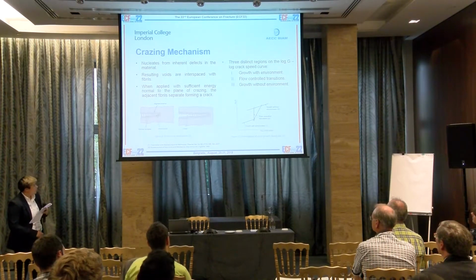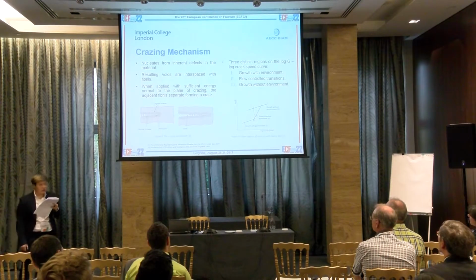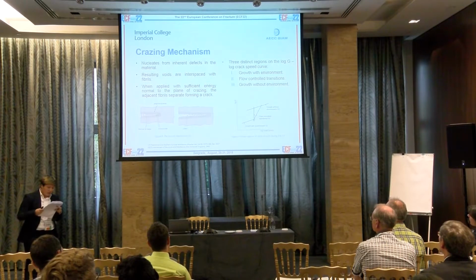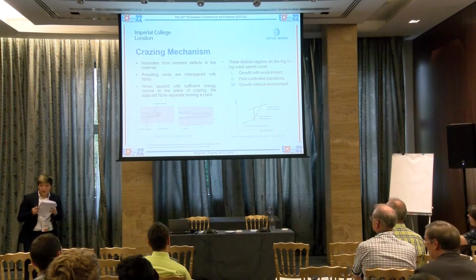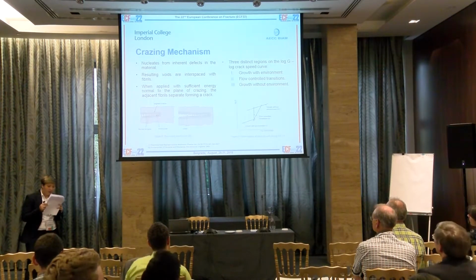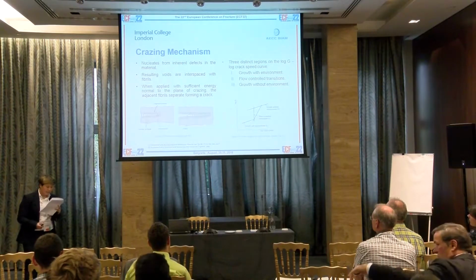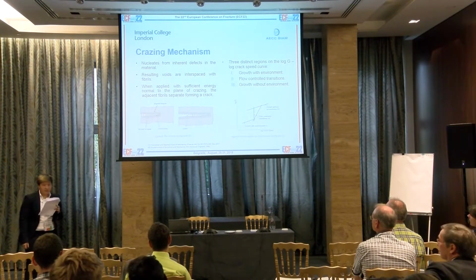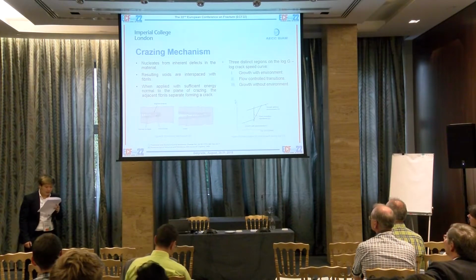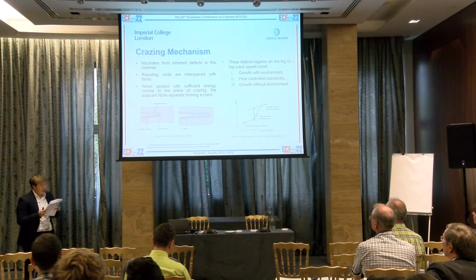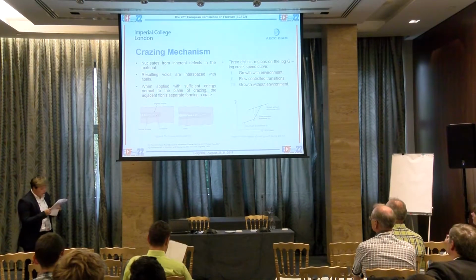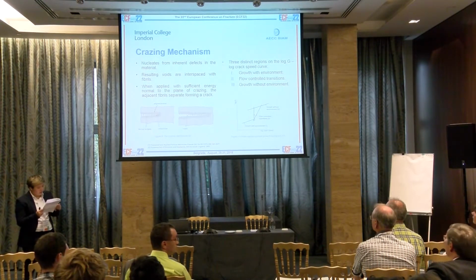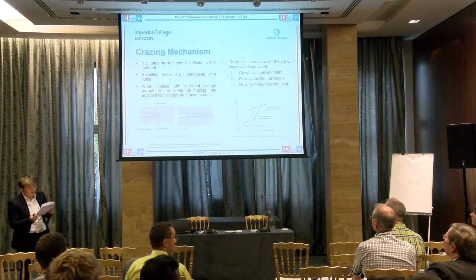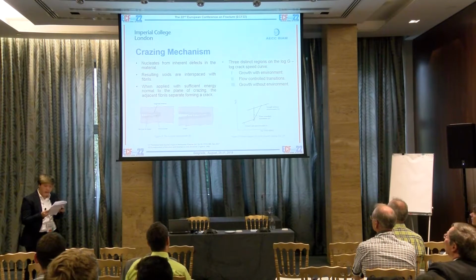Three distinct regions, labeled region 1, 2, and 3, can be found on the log G and log crack speed curve. When the specimen is first loaded in region 1, the crack propagates slowly, allowing enough time for the environment to flow and submerge the crack tip. Hence, the fracture toughness of the material is independent of crack speed. In contrast, during the fast crack growth observed in region 3, the environment does not reach the crack tip. Thus, the crack growth in this region is identical to that in air.